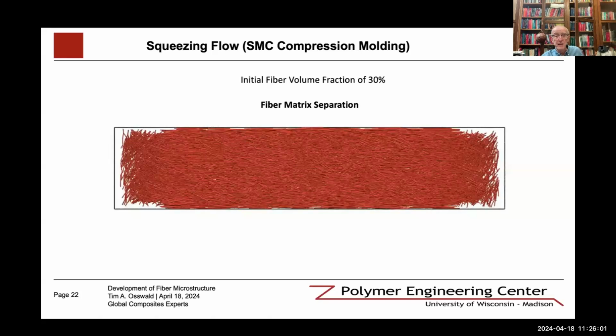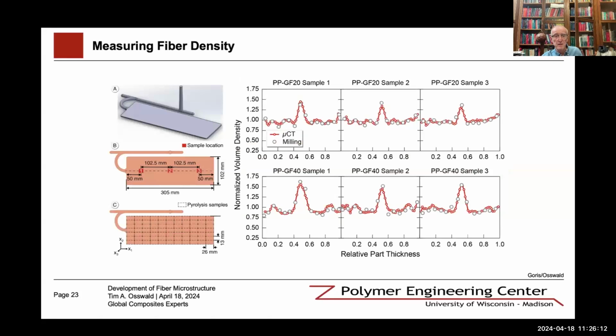And software today does predict fiber matrix separation, but in many cases it doesn't lead to the actual distributions that are seen in parts. So the first thing that I'll show regarding fiber matrix separation is, again, the three samples, 1, 2, and 3, for two different fiber contents, 20% glass fiber and 40% glass fiber.